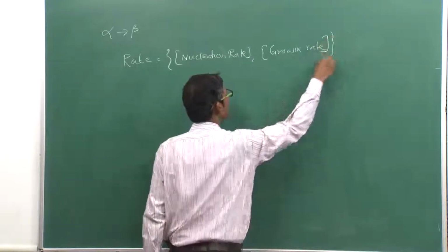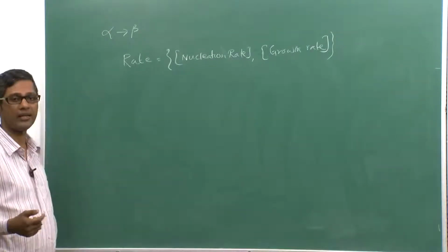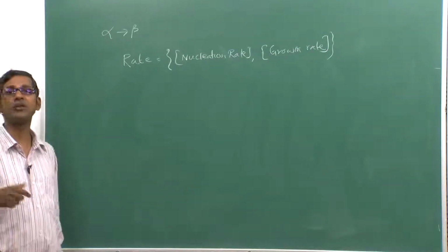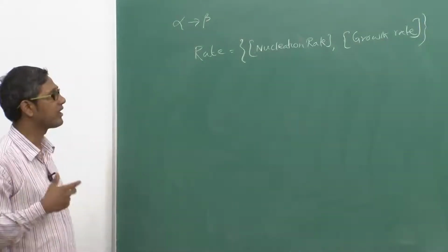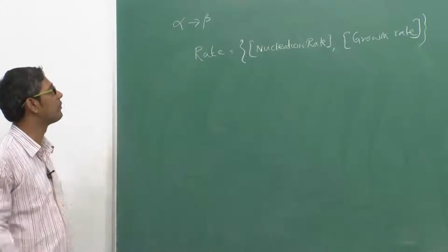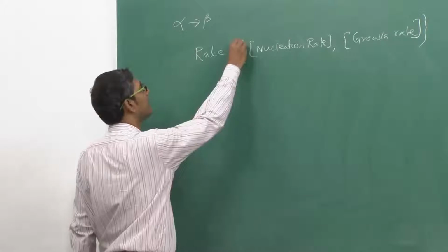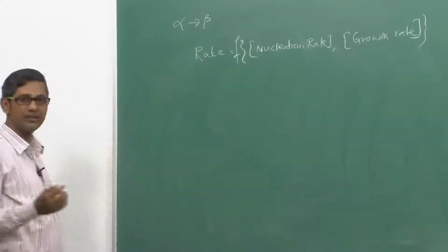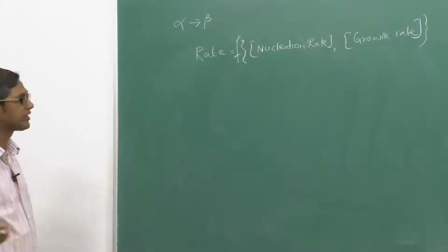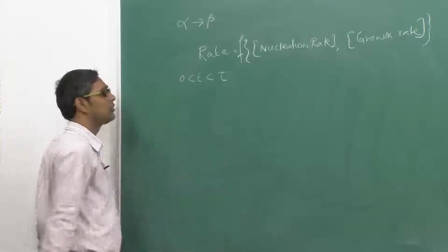As I said, the growth of these strain-free grains is basically dictated by the grain boundary energy. Small grains have a larger grain boundary area, so to reduce that, grains start coalescing and growing. So finally the rate of the whole process depends on the nucleation rate and the growth rate. Let us consider a very short time scale experiment in the time region of 0 to tau.